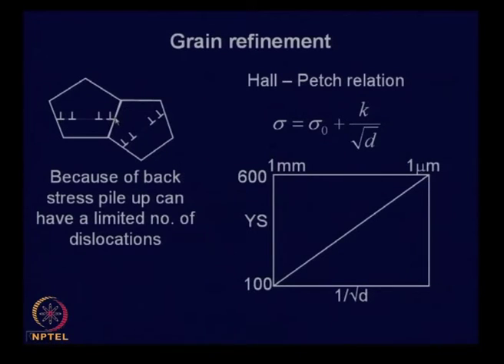here this dislocation stops, and a pile up develops, and this also leads to strain hardening, and depending on the size of the grain, it has a limited capacity. It can accommodate only a limited number of dislocations, and this grain boundary also has a finite strength, and if this number of dislocations increases, stress on the grain boundary, the local stress, gets intensified, and it can move into the dislocation and this area of grain boundary, or it can move from here to the next boundary, it is possible.